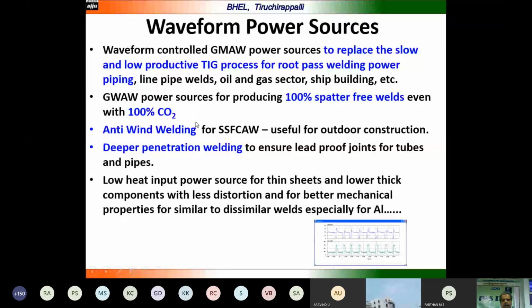Anti-wind shield welding, that is self-shielded flux-cored wire, can also be used for outdoor construction here. Deeper penetration welding to ensure leak-proof joints for tubes and pipes can be achieved. Low heat input power source for thin sheets and thinner components, with less distortion and better mechanical properties, for similar to dissimilar welds, especially for aluminum and its alloys, can be achieved by using this waveform controlled process.